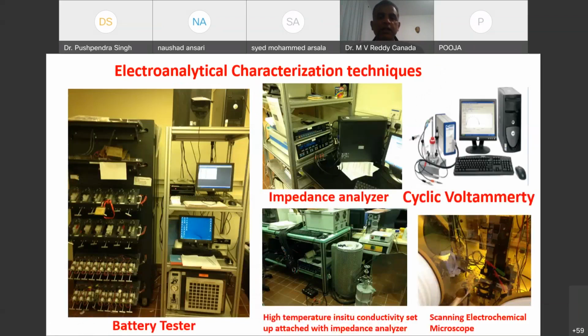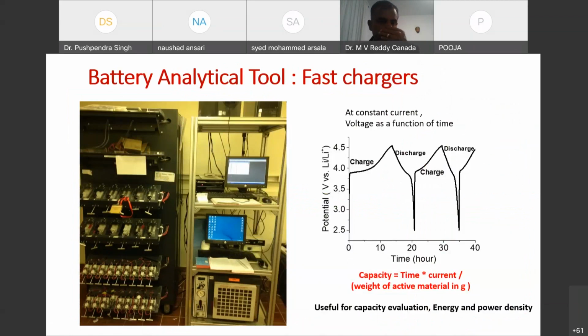Regarding battery characterization, I think we need a battery tester and impedance analyzer, and also other techniques like cyclic voltammetry, and for example, if you want to see the conductivity measurements, you need something like a furnace or two-probe conductivity setup. So what the fast charger is, is nothing but this particular setup. It will monitor the voltage from the lower limit to the higher limit, and it will maintain a constant current, and the capacity we can calculate based on time multiplied by current divided by the weight of the active